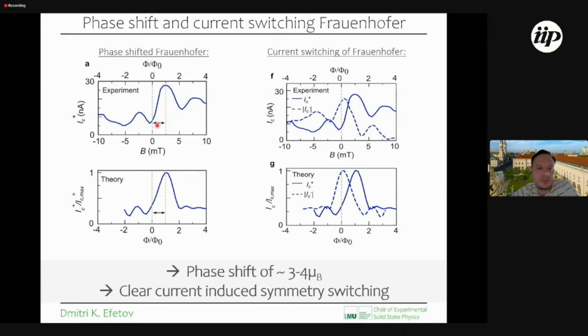So first of all, we realize that we have a phase shift of the Fraunhofer. If we look at the 0th order current peak in our Fraunhofer, it's phase shifted from 0 by around 3 millitesla, which corresponds to around 3 to 4 Bohr magnetons. This is, again, much bigger than what you expect from a spin ferromagnet, but it's consistent with the orbital magnetic state that we propose. And the other thing, which is even more striking, is the current switching of the Fraunhofer. Depending on the sweeping direction of the current, we can have a phase shift which is induced just by the sweeping direction of the current. And this is, again, in line with what was previously observed for these orbital magnets.